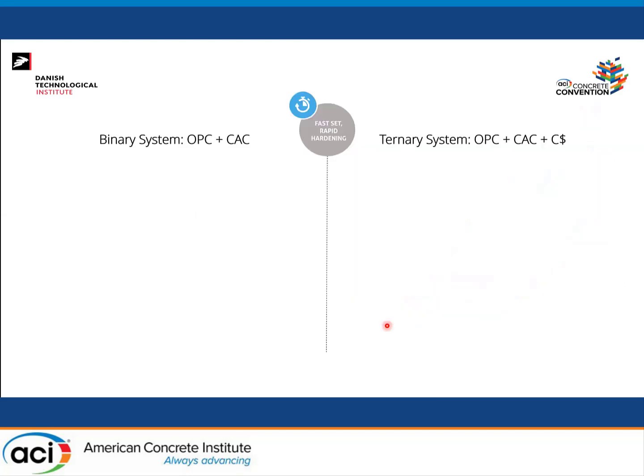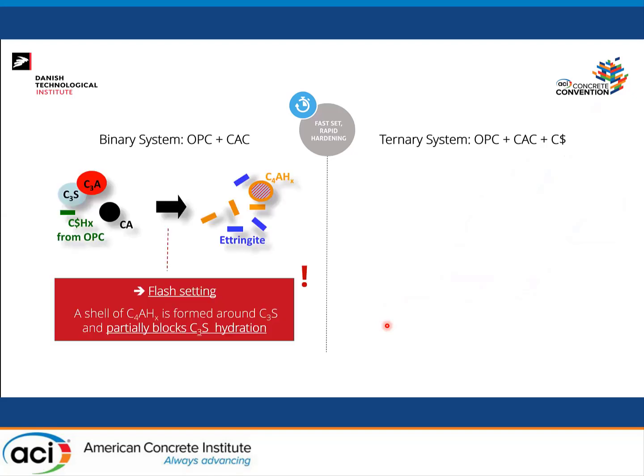So before I go into details of the mixing nozzle and the printing setup, there is just one aspect to highlight in terms of the hydration system on binary systems and ternary systems. Even though we were aware of that, of course, we still did the test using binary systems with OPC and CAC, and ternary systems with the 3 elements, I mean, adding the calcium sulfate. The problem with a binary system is that we can suffer from a flash setting effect that can block hydration of C3S in the long term.